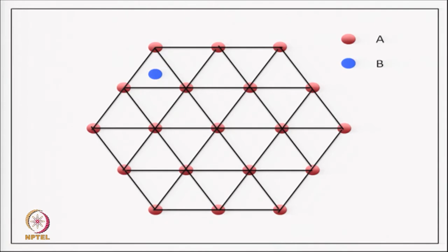Now, if I place atoms at all of such triangles which are pointing up, I get the next layer, the B layer. Still the third site is available, which is the C site. So, for my third layer in the hexagonal close packed stacking sequence, we stacked the third layer exactly above A. So, we got ABA, but that was one possible option.